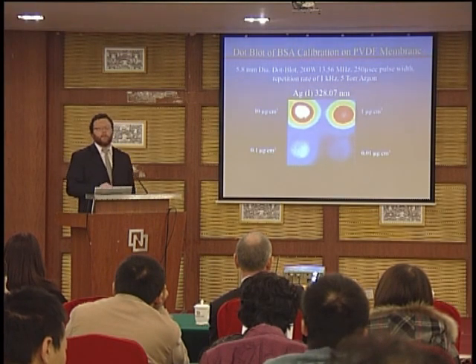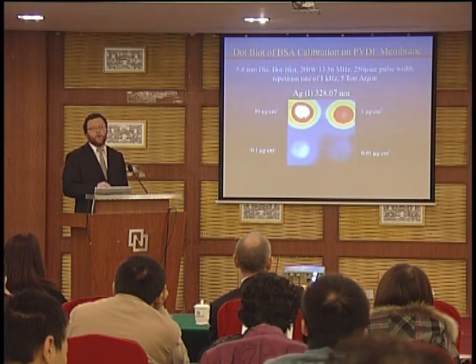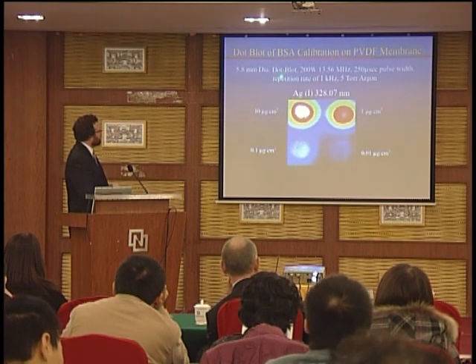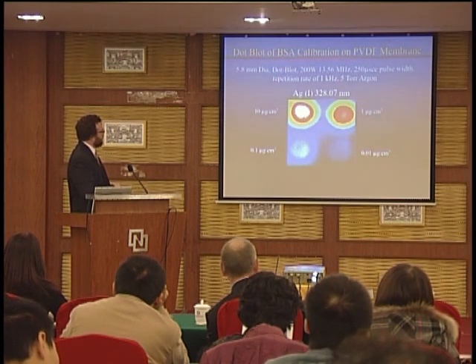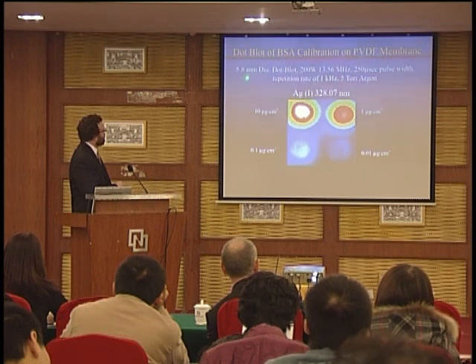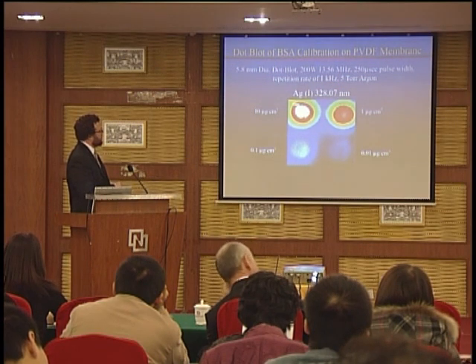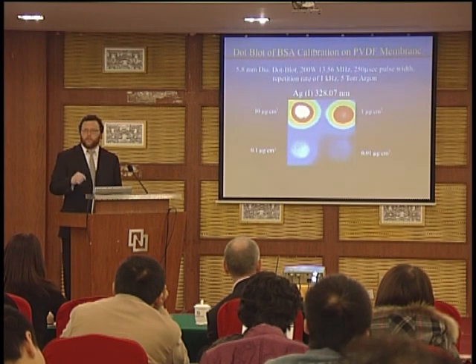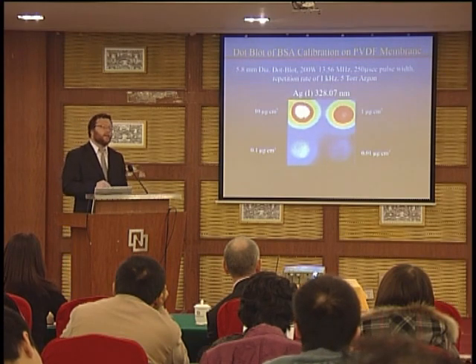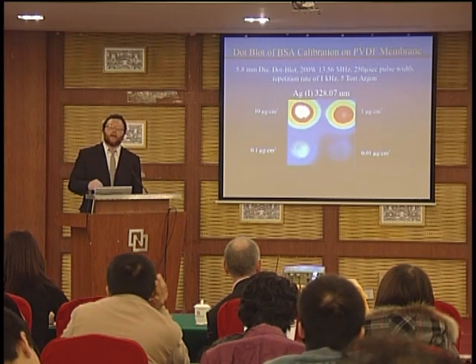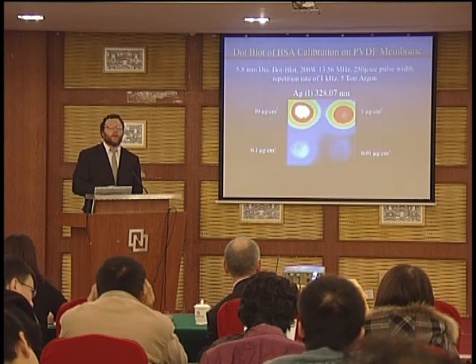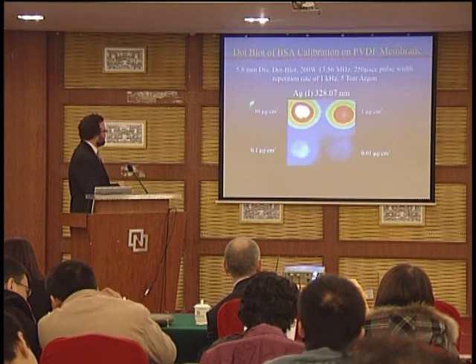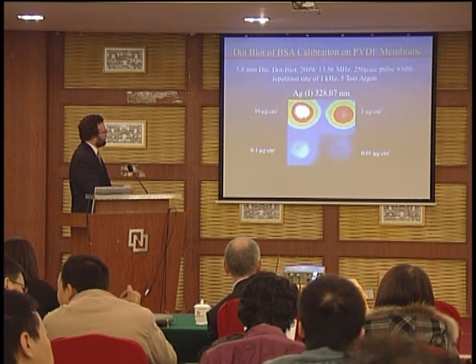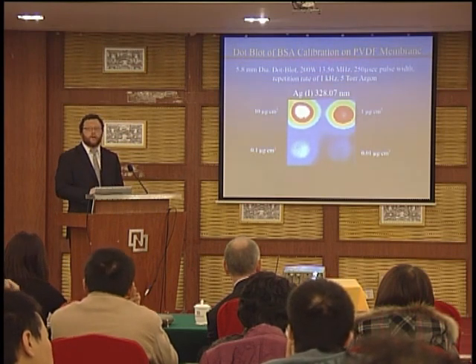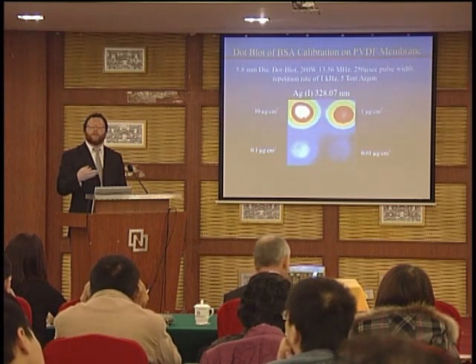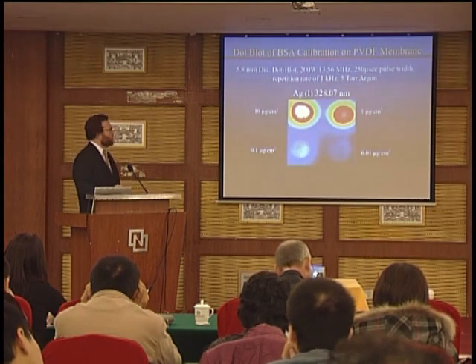This is a dot blot methodology that was typically used for quantitating proteins. This happens to be BSA, 5.8 millimeter diameter here. This is using a silver stain in order to visualize these species. And the idea here is to see how quantitative we can get in terms of increasing the detection limit and get proportional response. So these different values dictate the concentration of protein that was laid down on the membrane. We silver stain them, and then we look at atomic emission of the silver stain material.